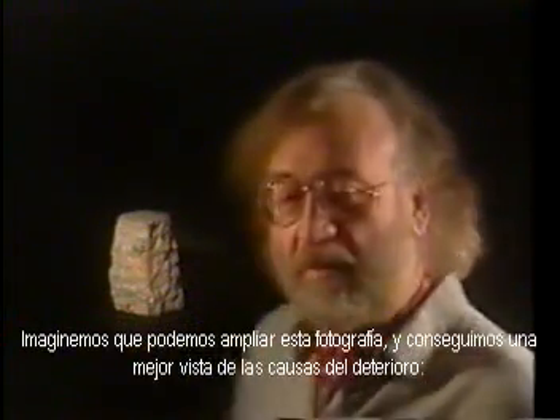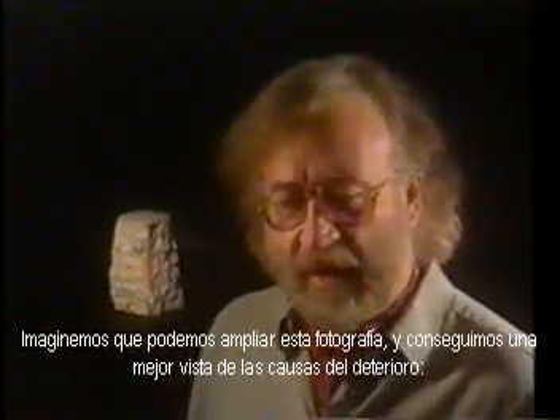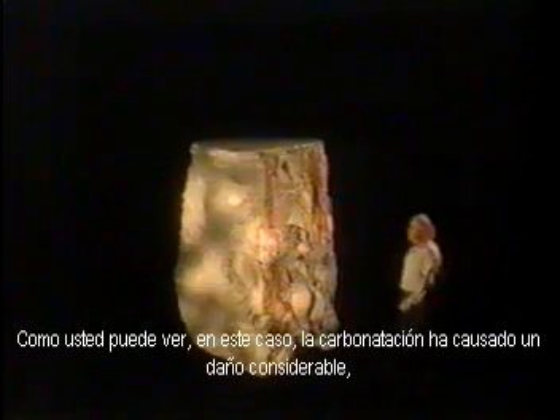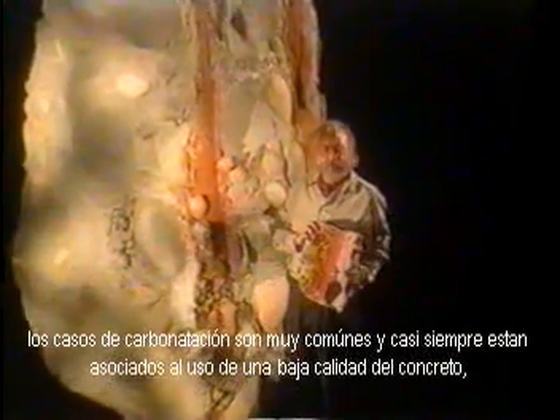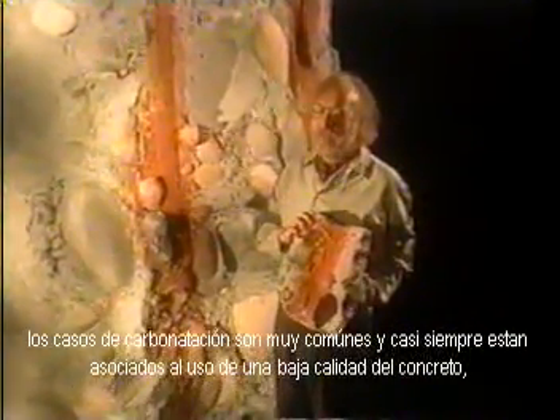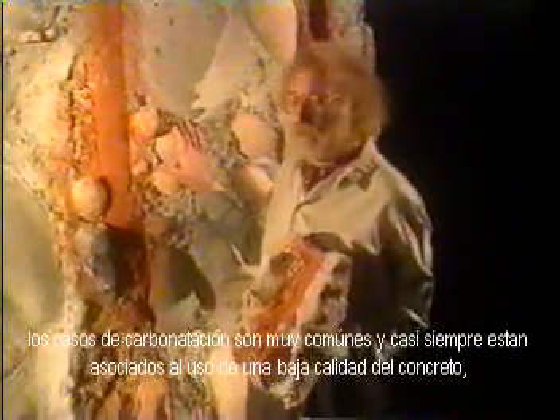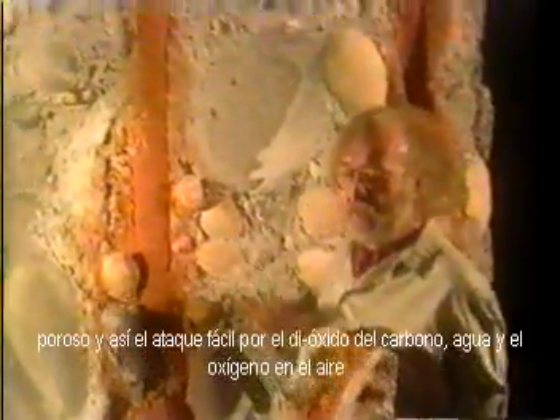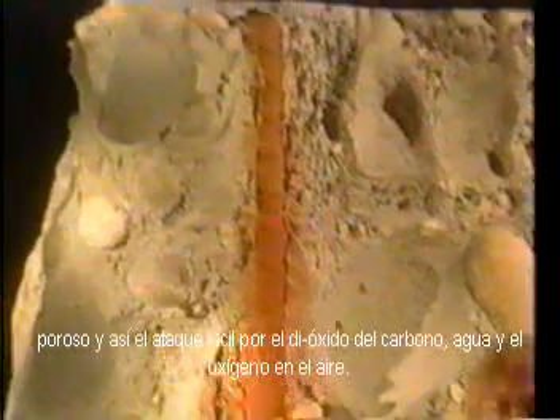Let's imagine we can blow up this picture and get a better look at the causes of the deterioration. As you can see, in this case, carbonation has caused considerable damage, causing the cover to come away completely. Cases of carbonation are very common and almost always associated with the use of low-quality concrete, porous and thus easily attacked by the carbon dioxide, water and the oxygen in the air.